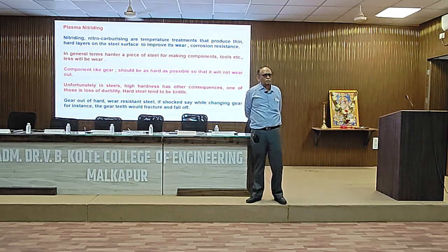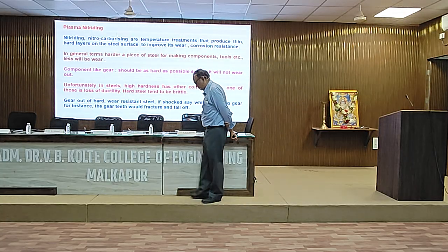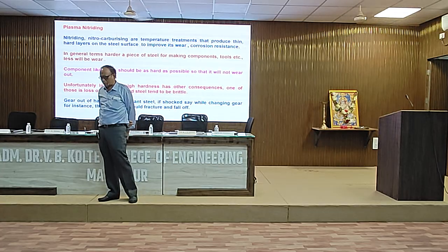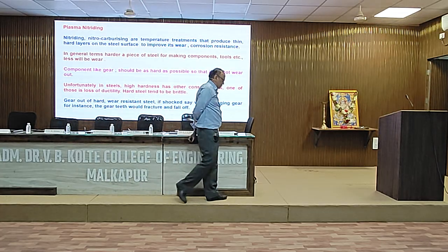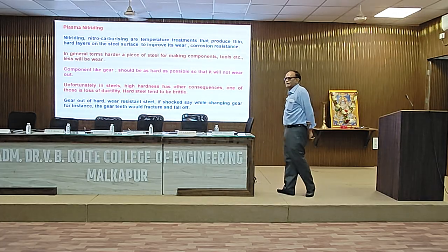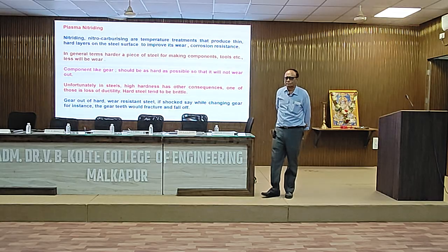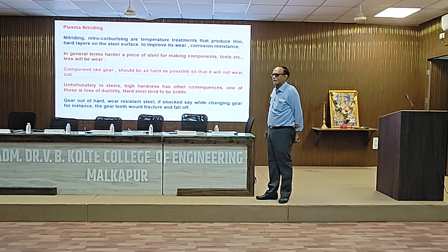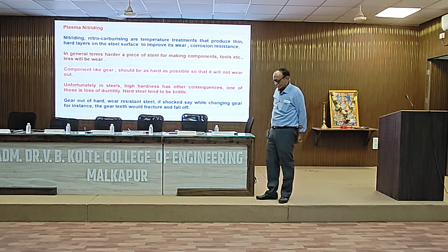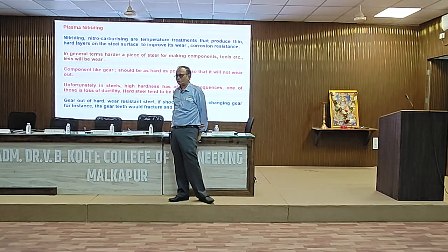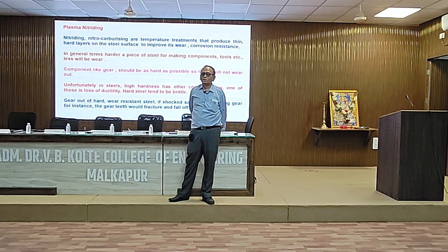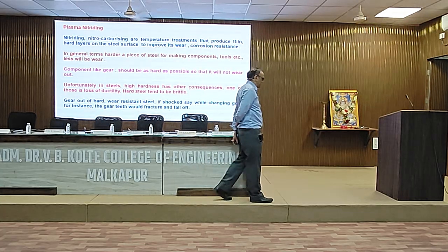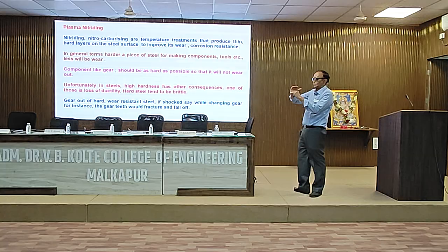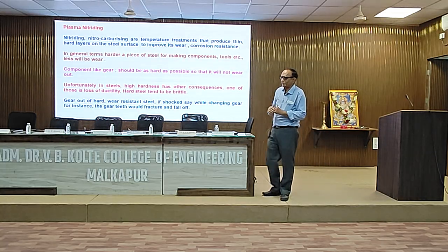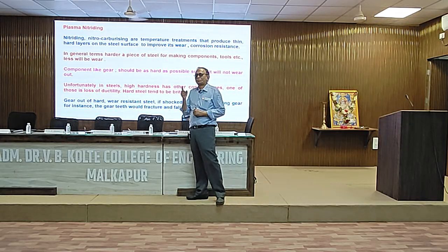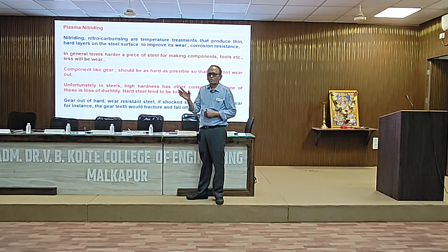Now you know steel has a composition of iron, a very small amount of silicon, chromium. Chromium is there, iron is there, silicon is there, and there are many other metals. Now if I can diffuse some nitrogen into this steel by some means, then I can make the nitrides, like iron nitride, chromium nitride, silicon nitride, and all these nitrides are ceramic phases. They are covalently bonded materials with high hardness. And if you can deposit or diffuse nitrogen into the steel, a nitrided case is formed onto the surface of the steel component, and its hardness can reach almost 8 to 10 gigapascal. Almost 4 times.